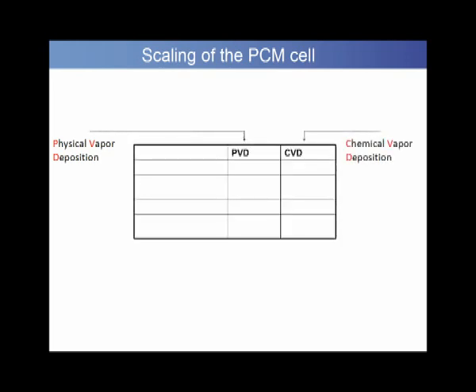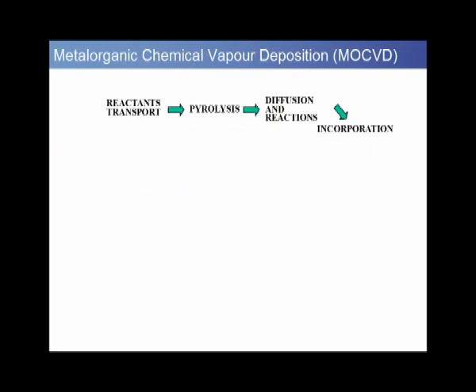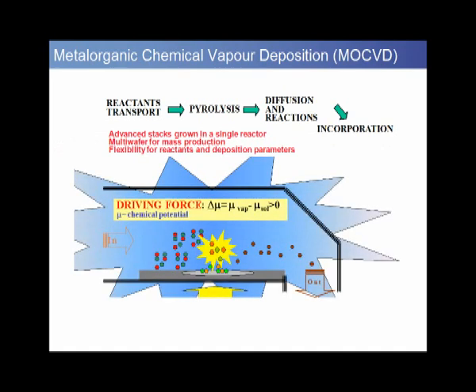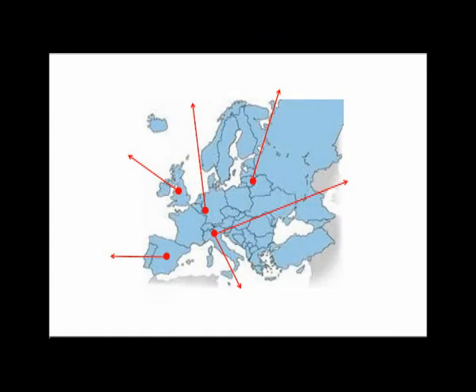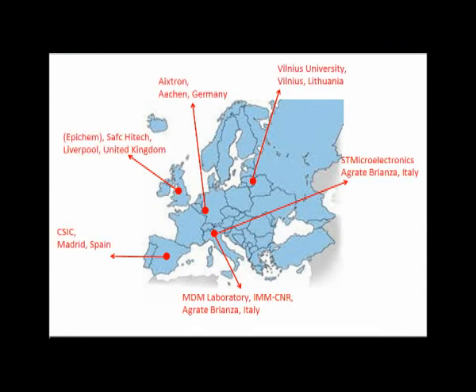To allow the scaling down of device dimensions, the chalcogenide material should be grown inside very tiny structures with high uniformity. A deposition technique alternative to physical vapor deposition is therefore required. In the project, we focused on metallorganic chemical vapor deposition, also called MOCVD, where the vapor phase transport is obtained by metallorganic compounds of the atomic species to be deposited. The CHEMAPH project was carried out by a consortium formed by 6 partners, including 1 academic, 2 national laboratories and 3 industries.